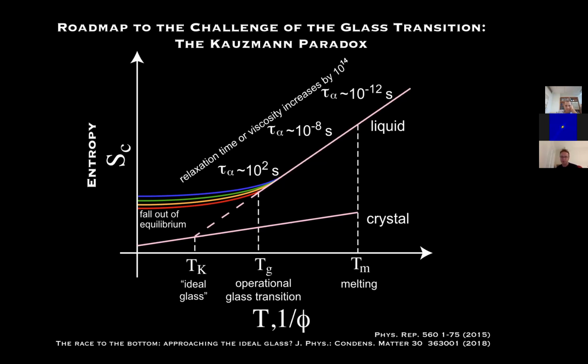So that's fine. And at high temperature, the liquid has a reasonably high entropy. But as we drop the temperature, on the x-axis is temperature, the entropy of the liquid drops. And the entropy of the crystal also drops, but not very much. Now, as we drop the temperature, there is a quantity which I've denoted as tau alpha. Tau alpha is the structural relaxation time of the material, and in a liquid, it's on the picosecond time scale. Well, when it gets to 100 seconds, we call the material a glass, and we say that it has undergone a glass transition to an experimental glass. This is the operational glass transition, Tg.